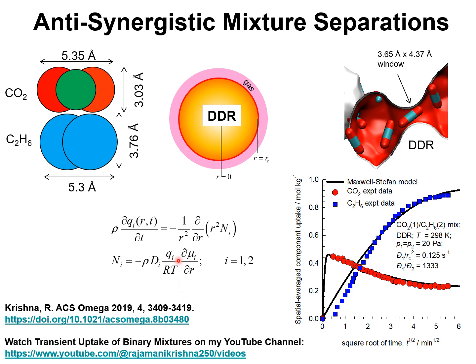In my presentation today, I'm going to discuss a different strategy for separating mixtures of CO2 from C2H6. This strategy relies on anti-synergy between mixture adsorption and diffusion in microporous crystalline materials. In particular, I'd like to consider separations using DDR zeolite that consists of cages separated by narrow windows with an aperture size 3.65 angstrom.